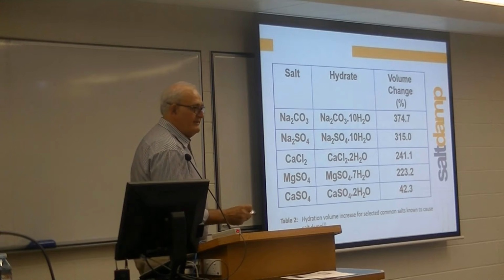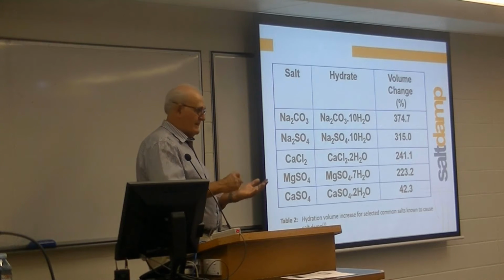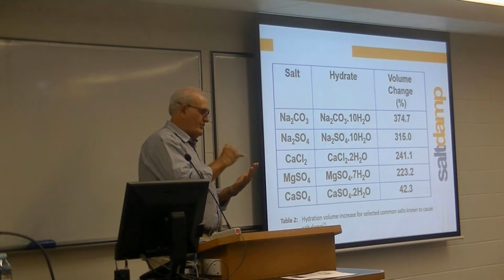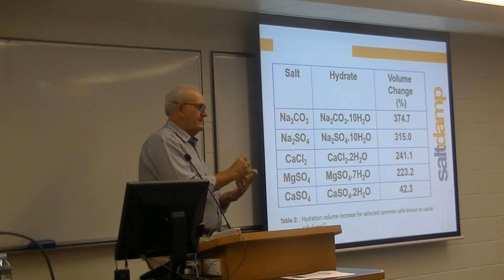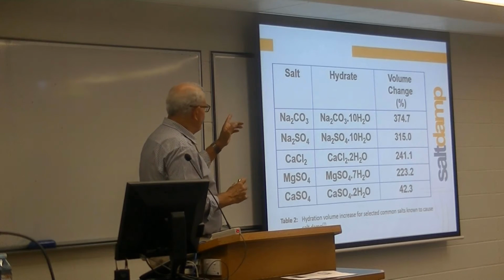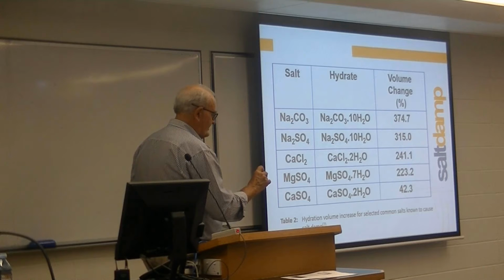So you have no hope of stopping this from happening while all the conditions are conducive to salt attack. Salts plus moisture plus a permeable medium for the saline solution to pass through, and then of course you must have that evaporative surface. And this is how the evaporative surface gets attacked, because these salts are left behind.